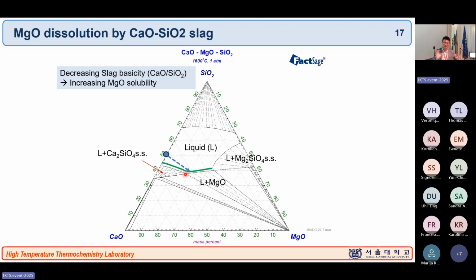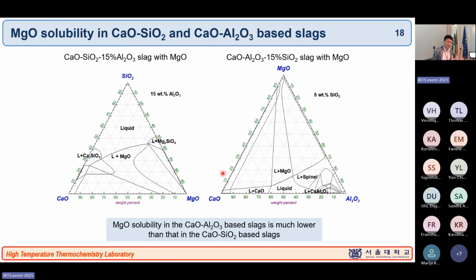And you can change something also, but at least we can run all these kinds of MgO saturation curves from the phase diagram. And depending on the CaO to SiO2 ratio, you can have different amounts of MgO saturation. So this kind of ternary phase diagram gives you the idea about how to control how much MgO dissolution I can expect from my slag. And let's move to the quaternary. So this is the quaternary phase diagram: CaO-MgO-SiO2 with 15% of Al2O3, we fixed the alumina amount, and at 1600 degrees Celsius again.